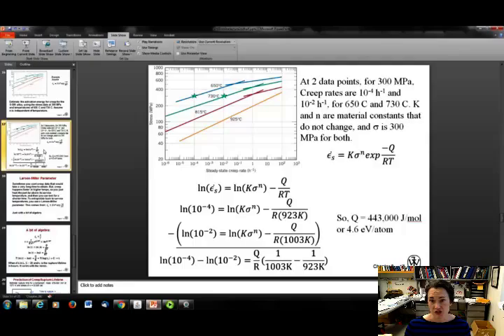And yet again, what I'm going to do is use my two data points. And here, my two data points are for the 300 megapascal data. If I look at that intersection of the data, then I get creep rates of 10 to the minus 4 inverse hours and 10 to the minus 2 inverse hours for 650 and 730 C, which were the temperatures cited. Now, K and N are those material constants that don't change because this is for the same material. All these curves are for the same material, the S590 alloy. So those can be assumed to be the same. And sigma is given as 300 megapascals for both.